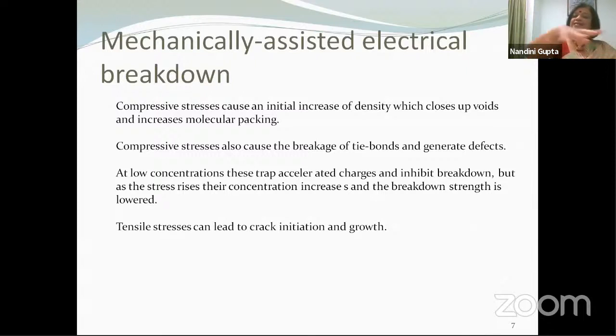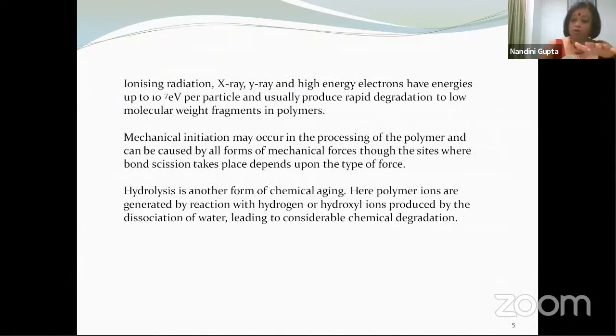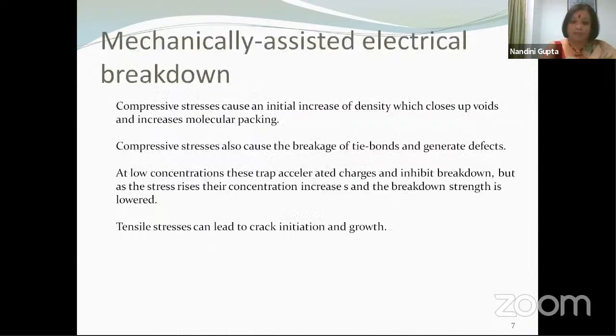When the material traps charges, every charge that is resident in the dielectric material will exert an electric field. So over and above the externally applied electric field, you would have a space charge field which is exerted by the trapped charges. And therefore, the electric stress in the material will increase. So that is what happens when you have compressive stresses leading to chain bond scission and defects are created. Dr. Reddy will be talking about defect formation and damage accumulation in materials this afternoon.